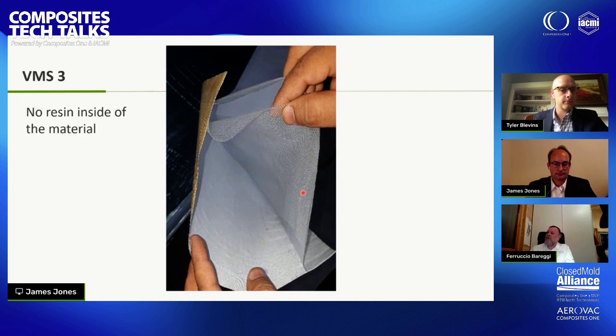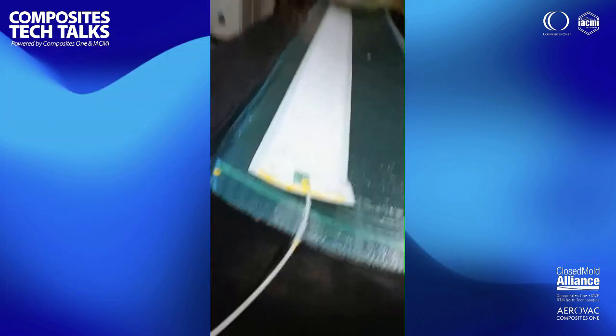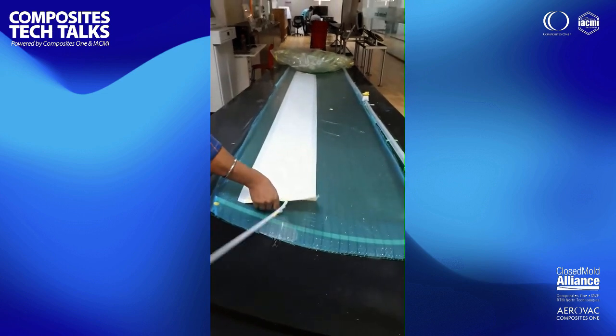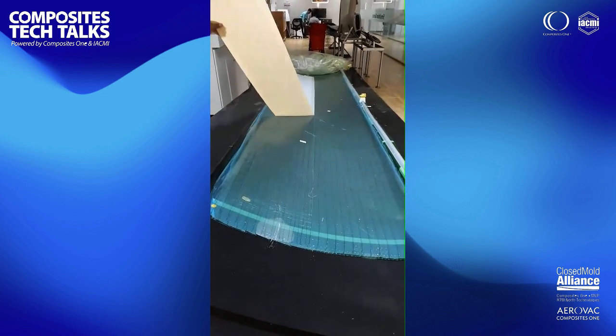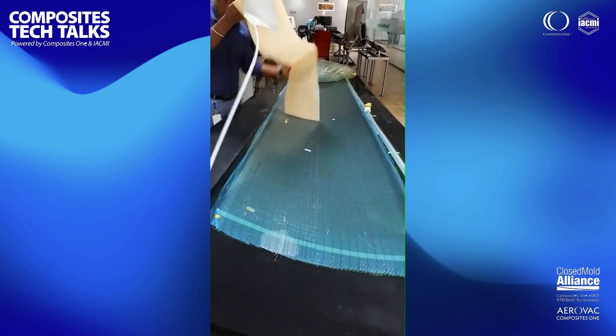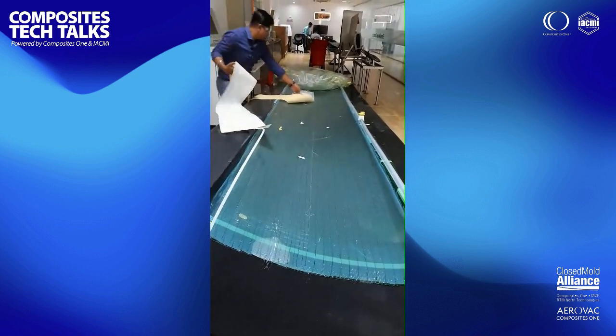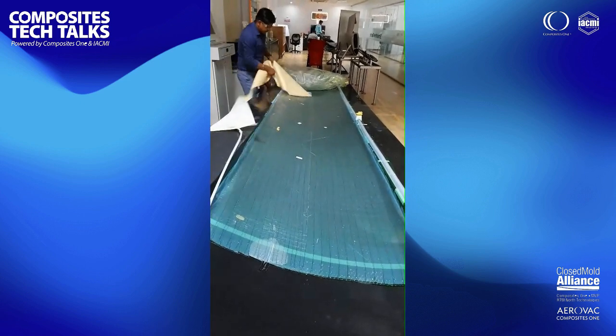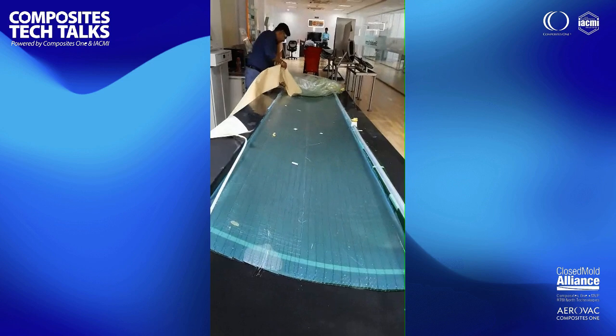You can see that, first of all, there is no resin at all inside the microporous vacuum line. So the vacuum mesh is totally dry. So it means that you are not dragging out any resin from your system. And also from the video that you may see now, you can see that the part, first of all, is completely impregnated, totally saturated. The material, the VMS3, is extremely easy to release, and it is not leaving any remarkable print through on the part. So it's working in a very profitable way.